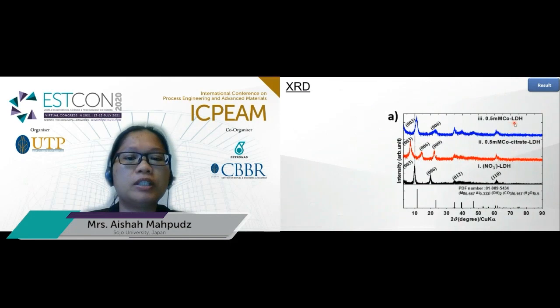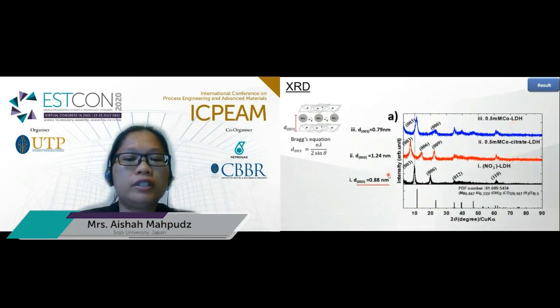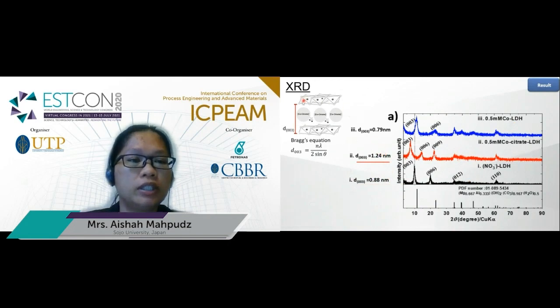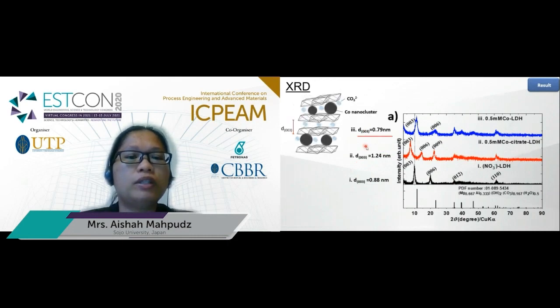For the nitrate LDH, the calculated basal spacing is 0.88 nanometer. After ion exchange, the basal spacing increased to 1.24 nanometer, which indicates a successful intercalation because the basal spacing expands to accommodate the larger size of the cobalt citrate ion. Following that, after reduction, the basal spacing obtained here is 0.79, and this represents the basal spacing occupied by the carbonate anion.